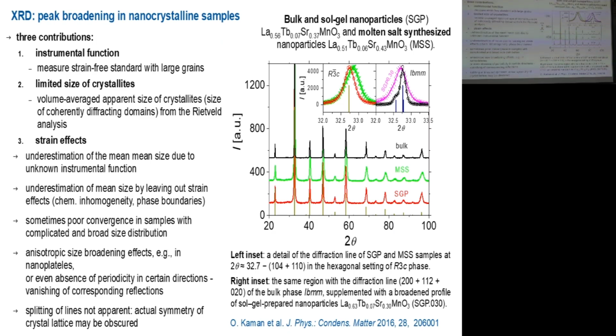And there are many important issues, but I think we should move forward. I would mostly point out one issue. This line broadening is very useful for this analysis of size of crystallites, but on the other hand, the line broadening can obscure your XRD pattern in terms of the symmetry of the crystal structure.